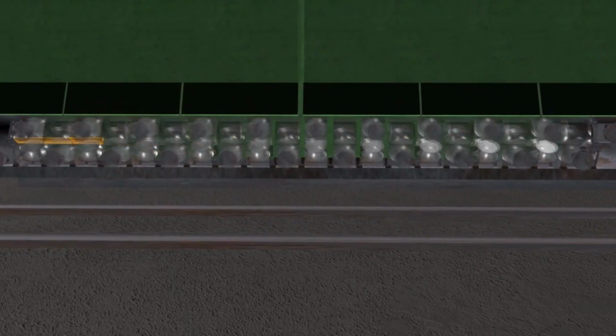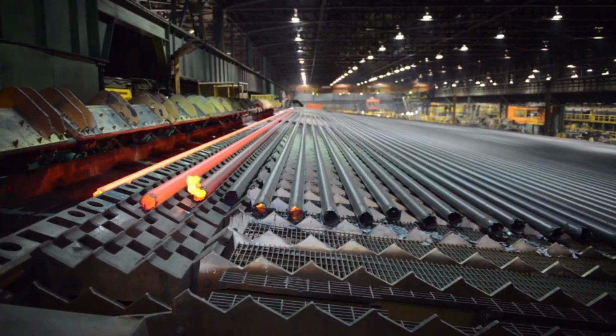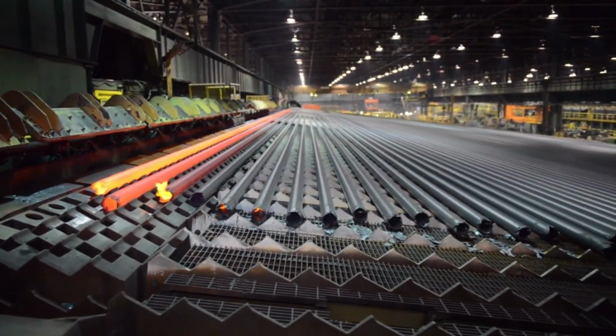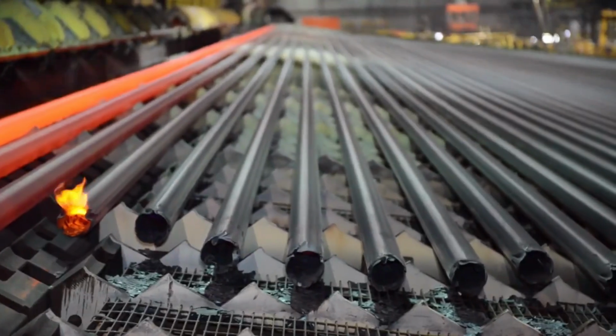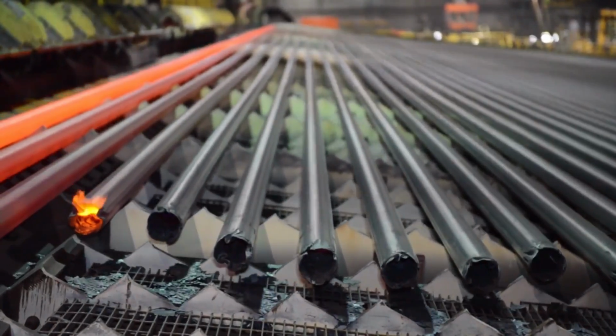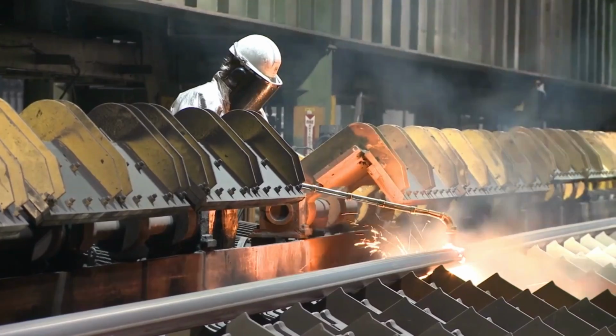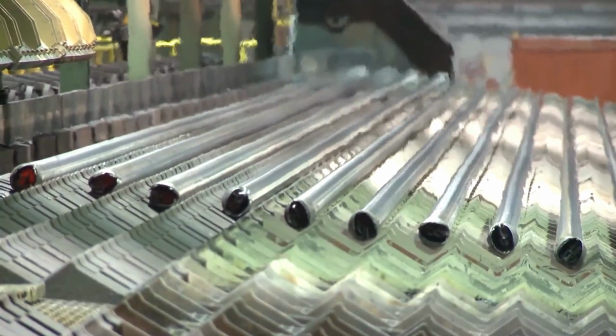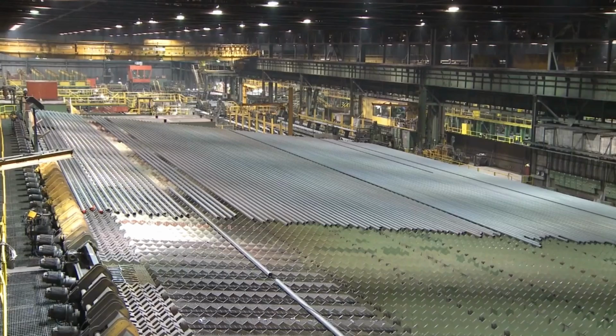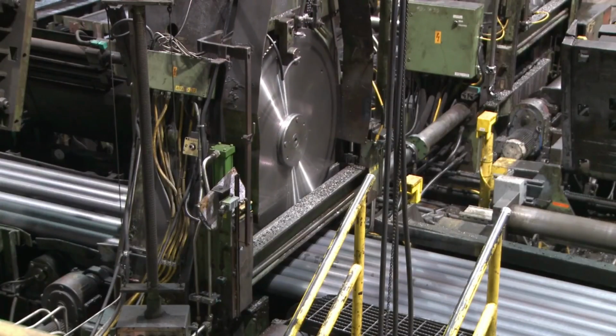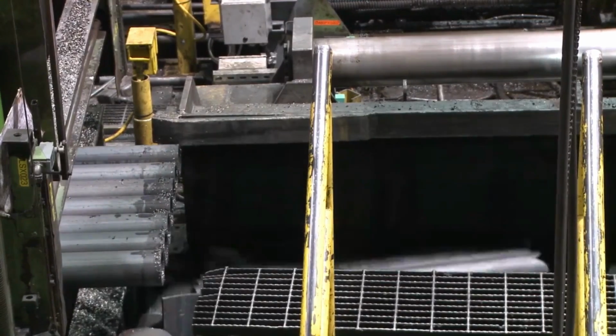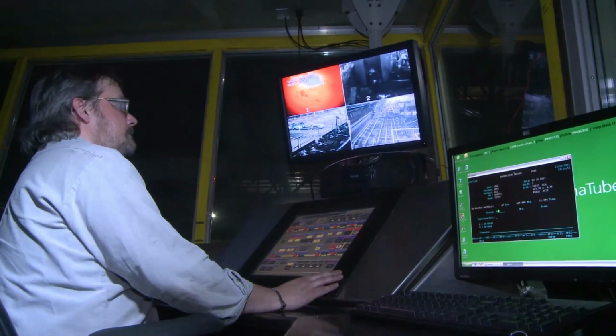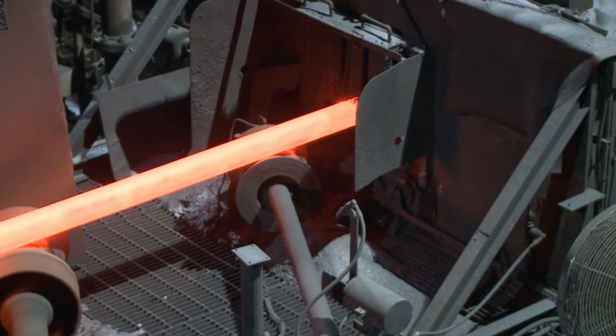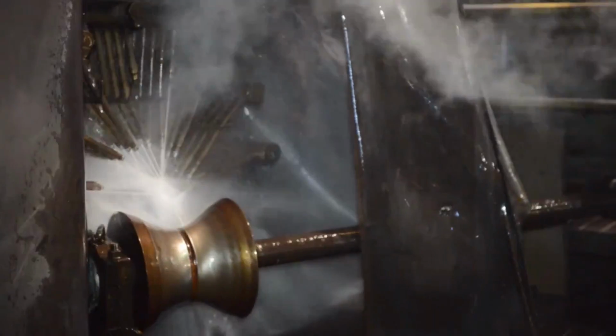The finished outside diameter of pipes produced at Tenaris Algoma Tubes range from 2 3/8 inch up to 9 5/8 inch. The hot roll tube is then discharged onto a cooling bed where samples are cut and sent to the on-site lab for testing. Individual pipes are now cooled to ambient temperature. After cooling, the pipe ends are cropped at the mill's cold saws and then transported to the heat treatment line for quenching and tempering. Here, the specified strength, hardness, microstructure, and impact properties required of high-strength tubular products are developed.